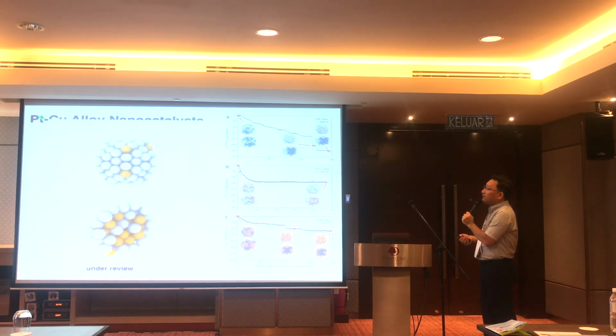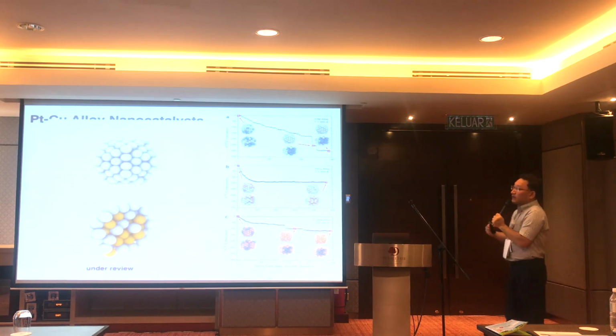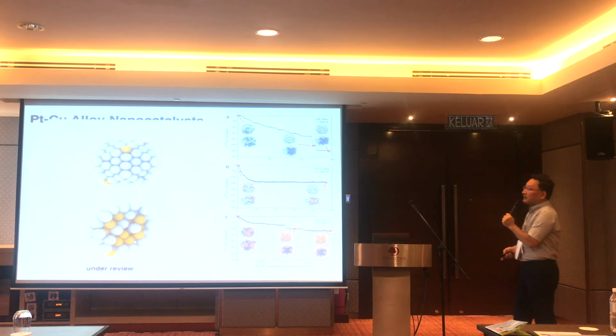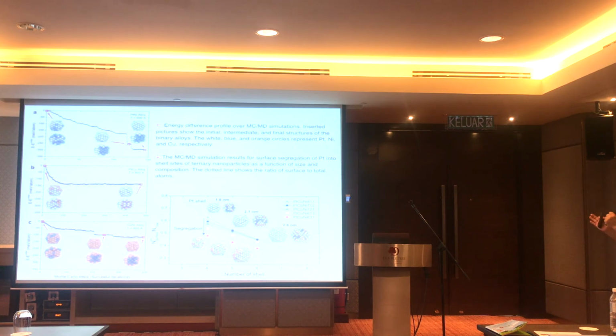Here, for example, platinum copper, what is the most stable structure? Once the machines understand the potential, they can easily predict the most stable configurations. It takes 1 second, 2 seconds, something like that. It's much better than the others. If you use the conventional first-principles calculations, it takes 1 month or 2 months. But if you do machine learning, you can get the result in 1 second, 2 seconds. Huge advancement, actually. Okay, so we found the best materials: platinum, copper, and nickel, for hydrogen-driven electric vehicle catalyst material.